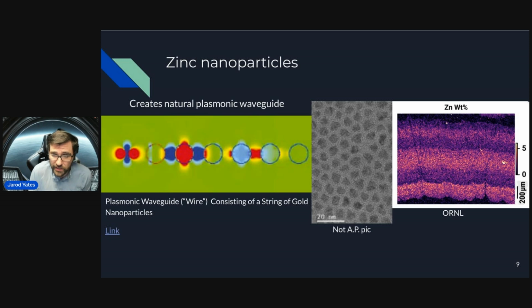On the right side, you can see I have a picture of the Oak Ridge National Lab report picture for whatever that's worth. And that is a much, much zoomed out picture. It is 200 microns compared to the 20 nanometers of the center image. But in that Oak Ridge image, you can see all of the bright pink spots. That's all the zinc. And since we know that it's 150 micron average thickness of zinc, you can see that this is actually a lot of layers stacked atop each other. This is not just like one single layer.